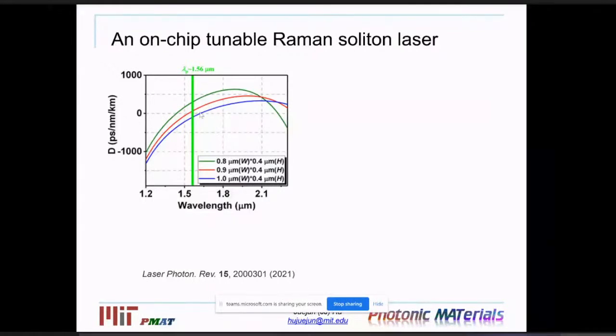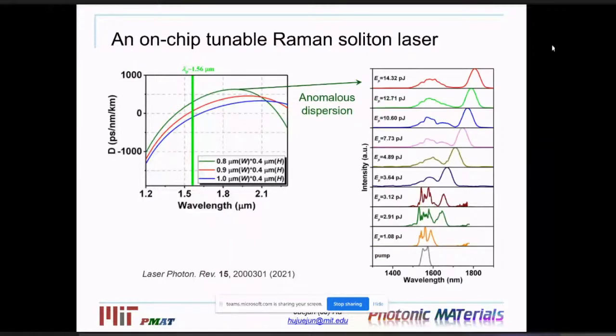What we're seeing here is that the 0.8 micron wide waveguide exhibits a large anomalous dispersion. But as you move to the wider waveguide, at 0.9 microns, you see the dispersion at the target operation wavelength almost vanishing, so we have a zero group velocity dispersion waveguide. And if you move on to 1 micron wide waveguides, then you have normal dispersion. It turns out that if you operate the waveguide in an anomalous dispersion regime, you get the interaction of so-called self-frequency shift of the Raman solitons.